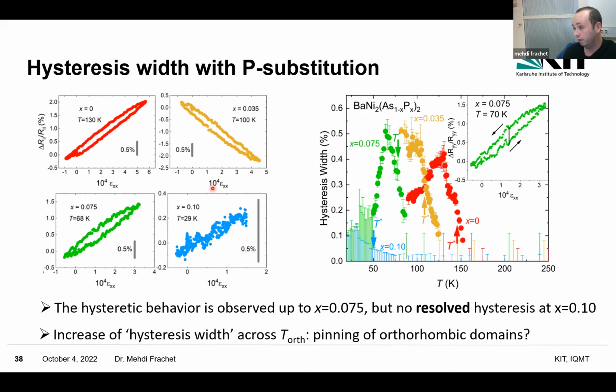The thing that we observe is that this hysteresis clearly increases strongly across the maximum of the elastoresistance. So the clear observation is that the hysteresis is only present when you have incommensurate charge order, right? But no, because in this 10% sample we don't observe any hysteresis, but there is still the incommensurate charge wave. Again, I don't observe it, but that does not mean it's not there. Especially in this 10% sample, everything is at low temperature, and at low temperature you can only apply small strain. The resistance is small, so the signal to noise ratio is smaller, which makes everything more complicated.